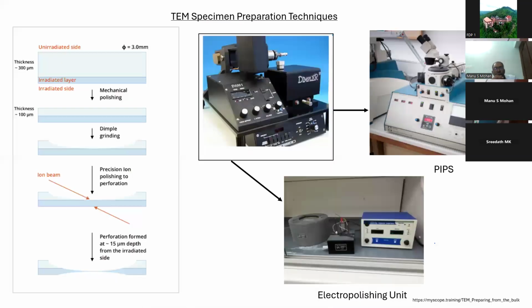Now I come to the preparation. The TEM preparation, unlike optical and SEM, as you know, those preparations take hardly a few hours at maximum. In industry, they prepare optical specimens by cutting, polishing, everything. If they are very fast, they may prepare everything within 10 to 15 minutes. An optical microscope specimen can be made ready like that. Similarly for SEM, a little finer polishing has to be done, so maximum half an hour to 45 minutes, the SEM specimen can be prepared.